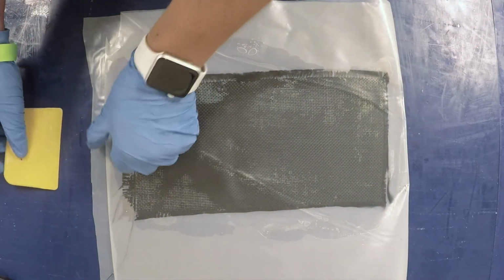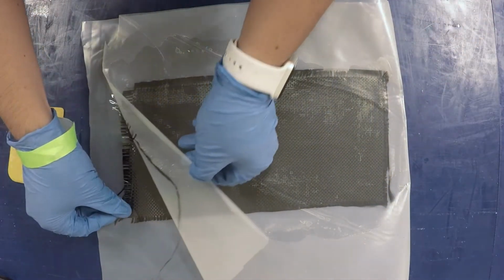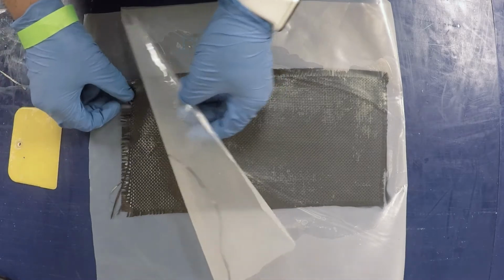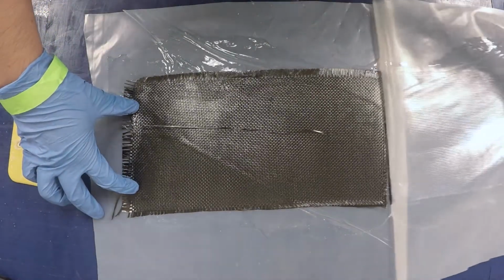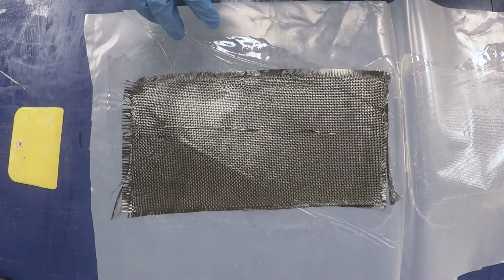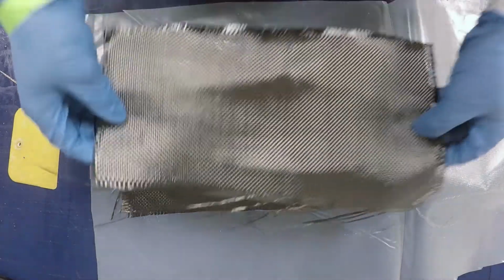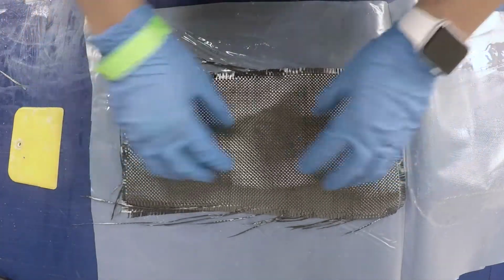Once you are satisfied with the appearance of your fabric, you can introduce the following layer. To do this, open the plastic while holding down your material. Be careful of fibers that can be stuck to the top layer of the plastic, as they will most likely distort the weave if they are pulled.